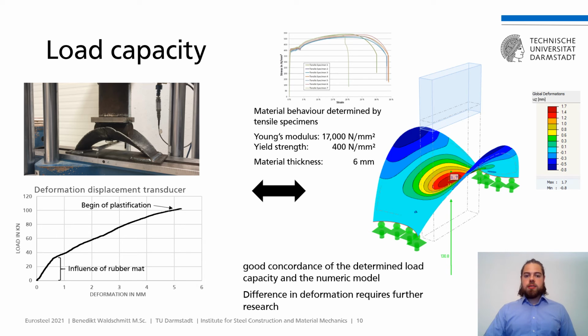For comparison, a numerical simulation based on third-order theory and material properties from tensile specimens was used. For a constant cross-section thickness of 6 mm, a maximum elastic deformation of 1.7 mm was calculated for load-controlled analysis, which thus significantly underestimates the actually occurring deformation. Possible explanations are the assumed constant cross-section thickness and the neglected influence of the thermally induced residual stress occurring during the printing process. This requires further research. Nevertheless, there is a good concordance between the load-bearing capacity determined from the numerical model and the compression test.